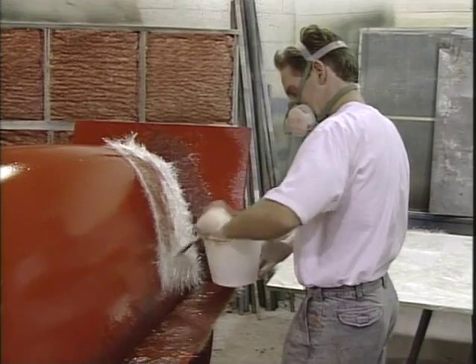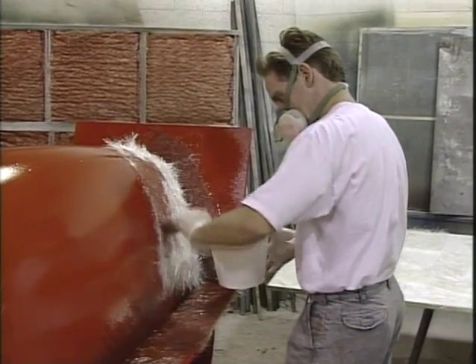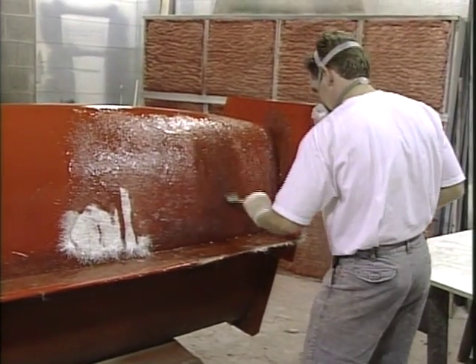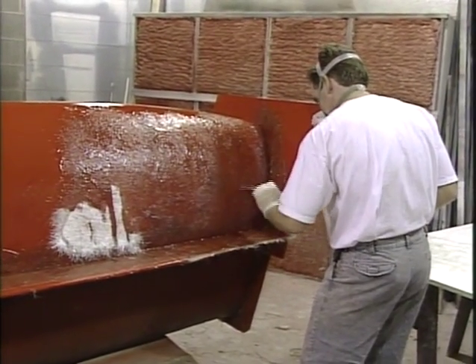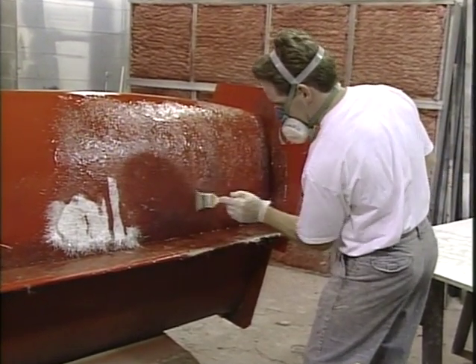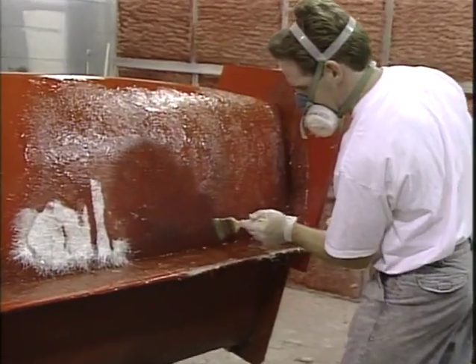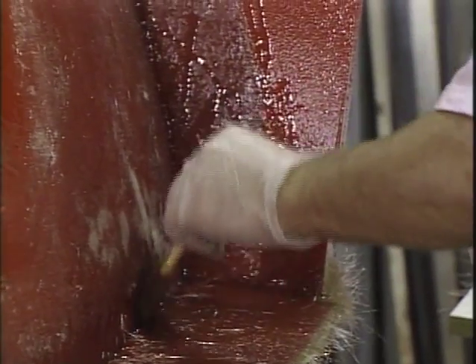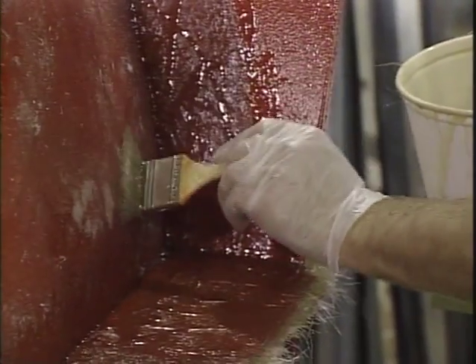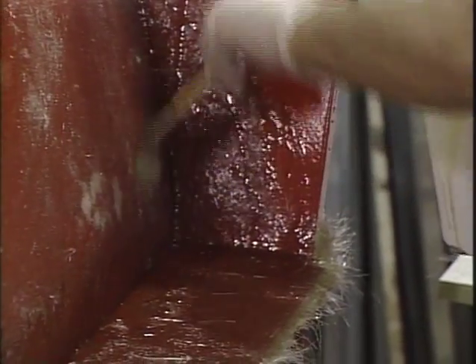over the plug. It is easier to work torn chunks over the contours than full lengths of mat. You will again lay resin on the surface and saturate the mat as well. Applying the mat directly with gloved hands is the most common approach and allows for the feel of the plug. Stippling with a brush and a groove saturation roller help to eliminate air. You will want to apply a total of 2 mat layers to the plug and the flange before continuing with the 10-ounce fabric.